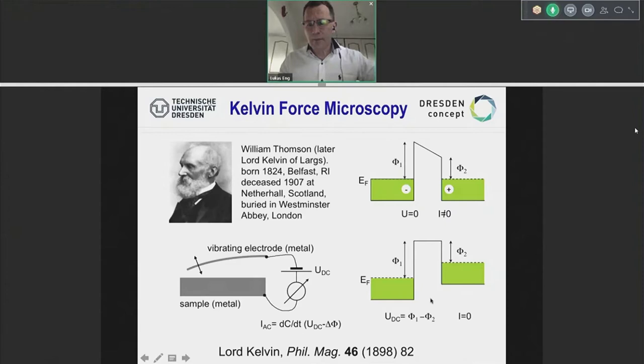Second example, you can say, well, I'm going to level off one of these surfaces by simply applying a DC voltage in such a way that my current I goes to zero. Or in other words, phi1 and phi2 are now lined up so that they form a straight line here. In other words, this is the bias that you apply to do the Kelvin probe measurement.